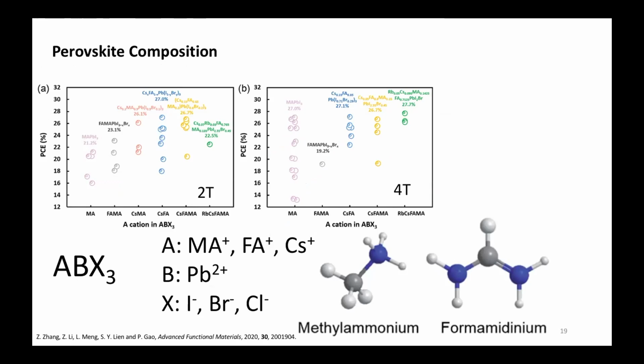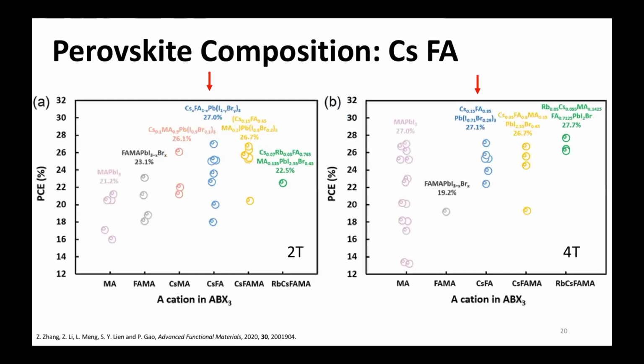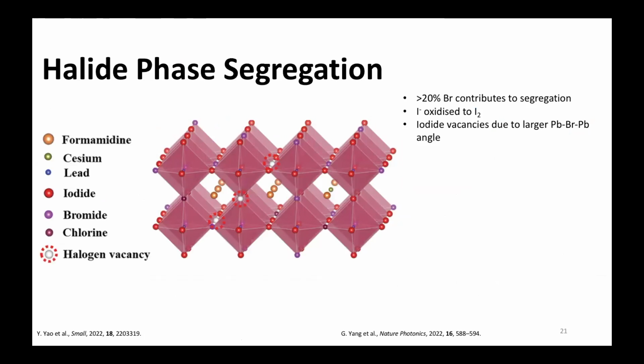If you look at the compositions that have been used a lot, then especially the combination of cesium and formamidinium is the most promising, that gives the highest efficiency. The cesium formamidinium combination is higher for both configurations. There are problems. One of them is phase segregation, that you get bromo and iodo rich domains. The ions move in the material and they segregate.